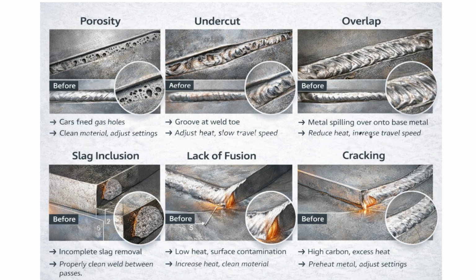Slag inclusions are non-metallic solid materials trapped in the weld metal. They result from improper cleaning between passes, incorrect electrode manipulation, or welding over heavy mill scale. Always remove all slag between passes and clean the base metal before welding. Lack of fusion means the weld metal hasn't properly fused with the base metal or previous weld bead. Causes include insufficient amperage, improper joint preparation, or poor electrode manipulation. Increase heat input and ensure proper electrode angles.